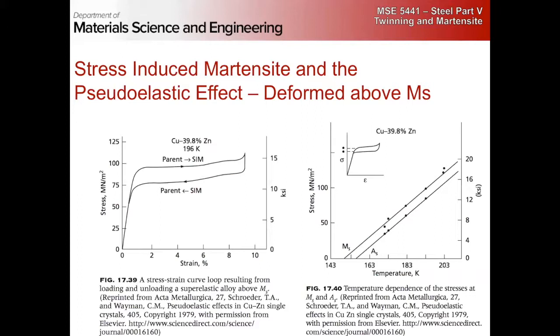The growth kinetics would be the same at a stress just a little bit above the critical resolved shear stress, we'll say. I don't believe that there actually is a critical resolved shear stress for twinning, but just above that, or 10 times as large, the twin growth rate would be the same.